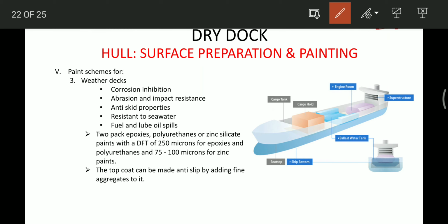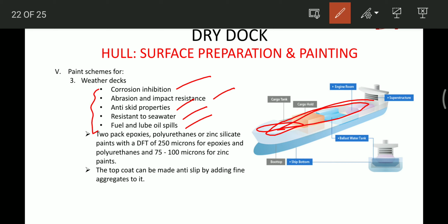Now the third is the weather deck, this top area. This area should have a corrosion inhibitor. Then this paint should have abrasion and impact resistance, skid property, and resistance to seawater and fuel and lube oil spills. So these paints can handle all these things. The coating which is applied is 2-pack epoxy polyurethane or zinc silicate paint with dry film thickness of 250 microns for epoxies, and polyurethane 75 to 100 microns for zinc paints. The top coat can be made anti-slip by adding fine aggregates to it.